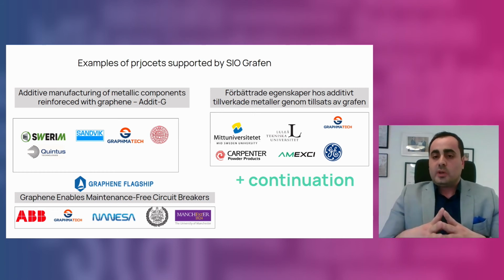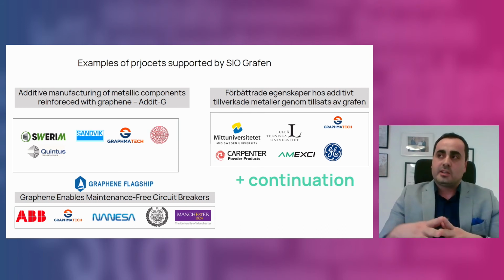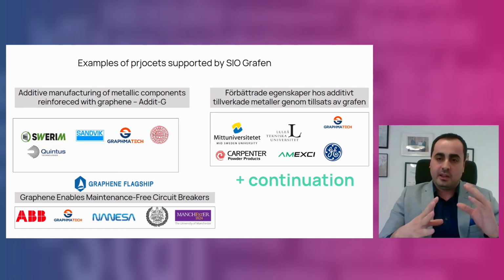The other project, which we got continuation for just recently, is steel and additive manufacturing. So in the first phase, we got really interesting results. We could 3D print the coated steel powder with the graphene. And we got indications that the graphene survived the selective laser melting processing and improved the tribological properties. So now we get a larger project, and together with the same consortium, we are going to make further investigations, and of course, at the end, see the commercialization aspect of this technology.